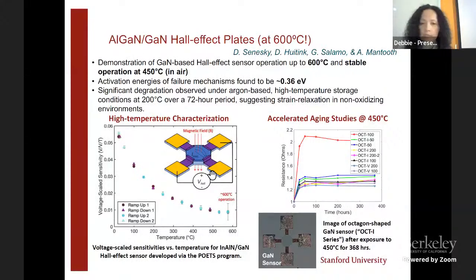And then we've also done short duration tests. So this is up to 368 hours. And then this is short duration tests where we cycle from room temperature up to 600 degrees C in air. And we can see the voltage scale sensitivity is overlapping, but these are minutes of tests, right? This is on a probe station and we're able to ramp up and down, but we want to do much longer aging studies. And this degradation here with temperature is due to the decrease in mobility, as we expect.